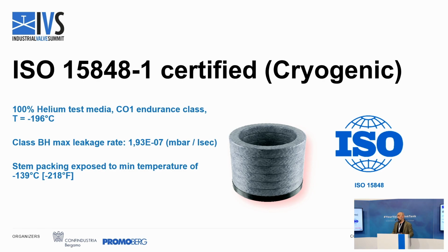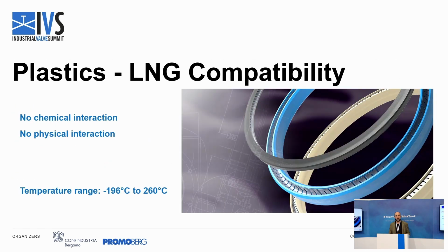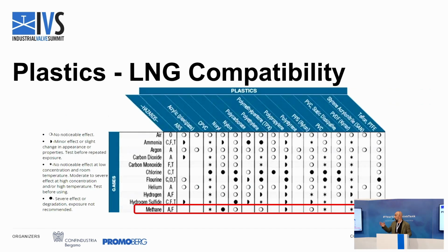Okay, the other material that we can use for the sealing in the cryogenic sector, of course, is the plastic material. We know that PTFE can go down to minus 196. Usually is not used the classic PTFE, but the modified PTFE, which has better performance at low temperature. The chemical interaction and the physical interaction is basically zero between PTFE and methane. We know that. There's plenty of examples in the literature. We have a lot of case study. Methane is used since very long time. So there's a lot of examples that allows us to say that PTFE is completely compatible